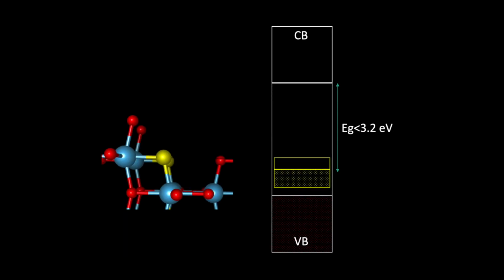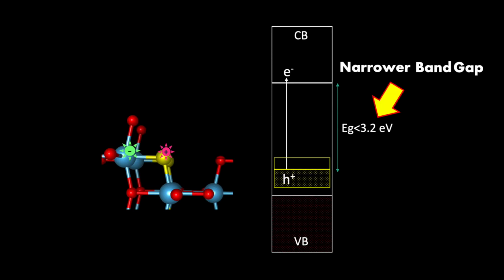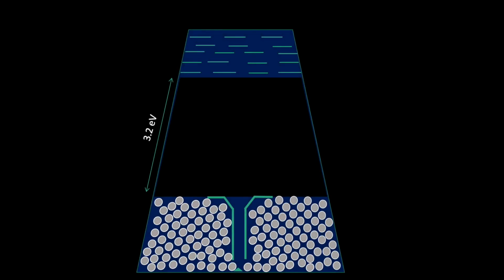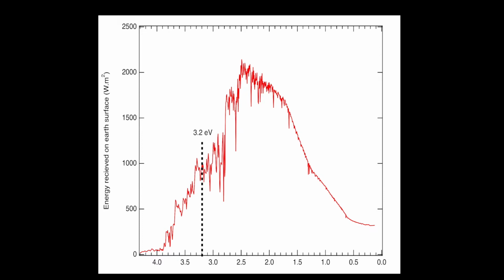With these new narrower band gaps, a lower energy photon in the visible region could also kick an electron into the conduction band, creating an electron-hole pair. This is known as the band gap narrowing effect. This is like we are adding a new ball reservoir in the black region and we don't need to flick the balls hard as before. In reality, because of this effect, a bigger portion of the solar spectrum could result in charge separation and theoretically, it could improve the photocatalytic activity of titanium.